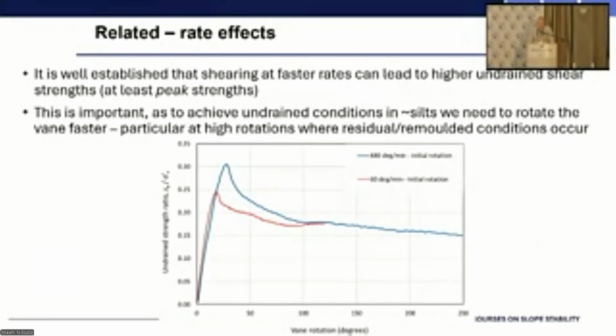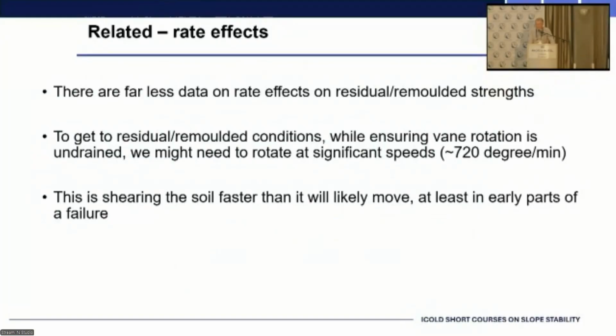There's also, we know, that you can get different stress strain post-peak type behavior depending on the rate of shear. Talked yesterday about the need to shear the vane fast enough to make sure we get undrained peak strengths. But then what about undrained large strain strengths? Do we need to then change the rate of shear of the vane during the test itself? There's not a lot of data in the literature on rate effects on the large strain strength. So we need to ensure that the vane rotation rate is capturing peak undrained as well as large strain undrained. And people are doing it at very high rates, 720 degrees a minute.